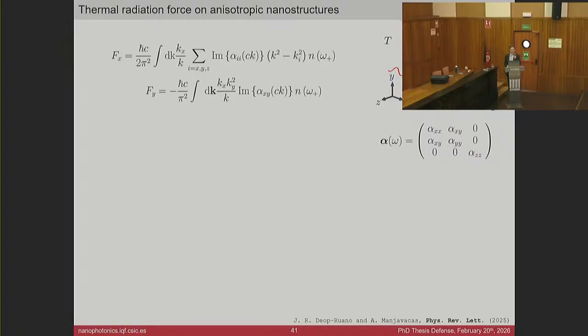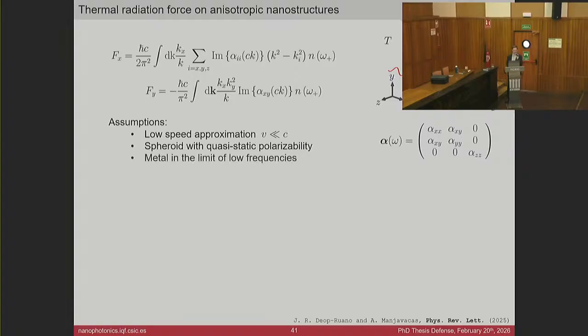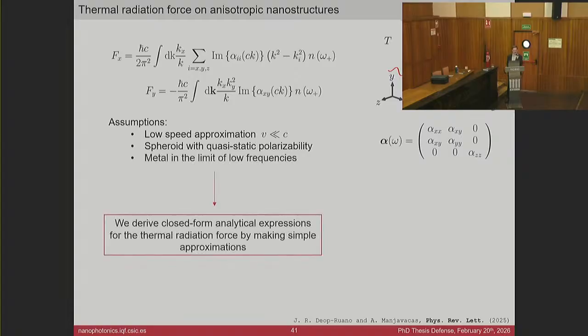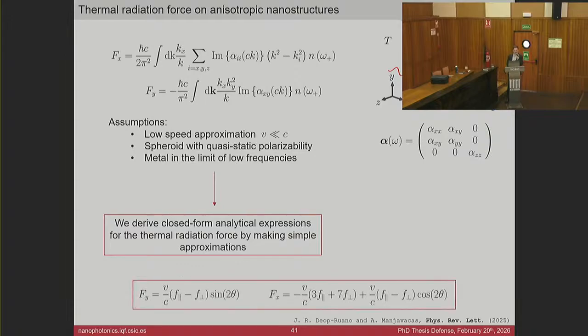Now, we are going to make some approximations to simplify these expressions. We are just going to make some simple assumptions. We are going to move at a velocity that is much smaller than the velocity of light. We are going to work at low frequencies. And by means of these simple, reasonable assumptions, we derive closed form analytical expressions that include an explicit dependence on the orientation, on the angle. And the amplitude of this force is going to depend on this small f function that depends, at the same time, on temperature, volume, the material properties through the conductivity, and also a geometrical factor accounting for anisotropy.